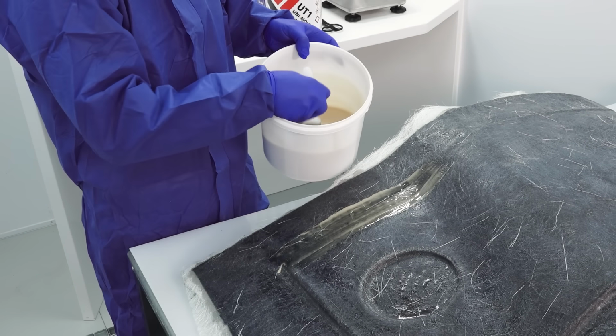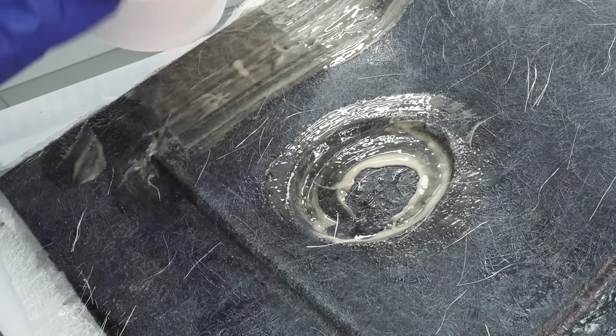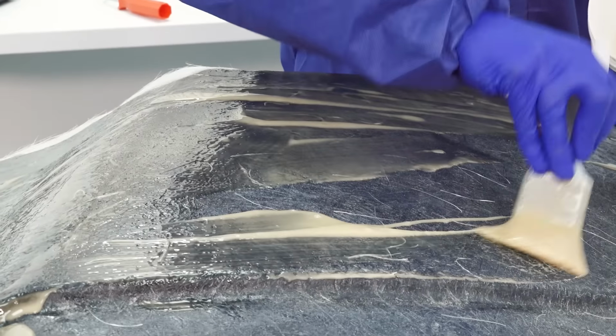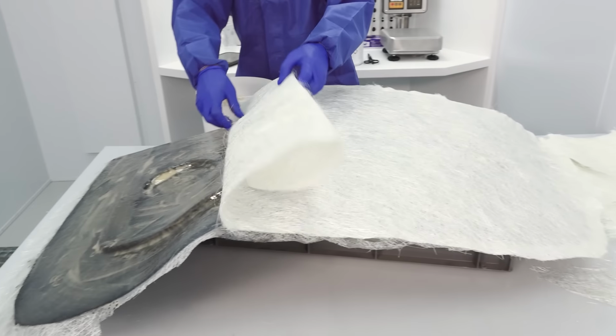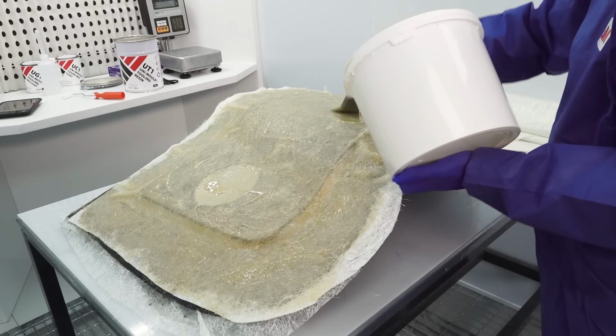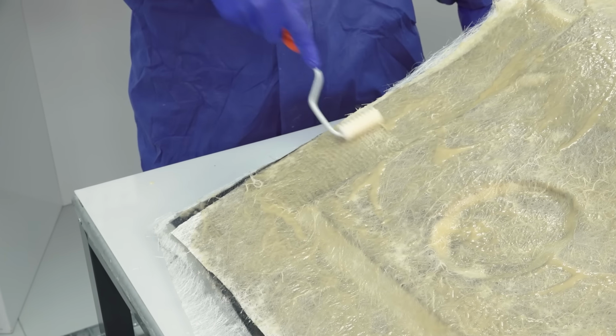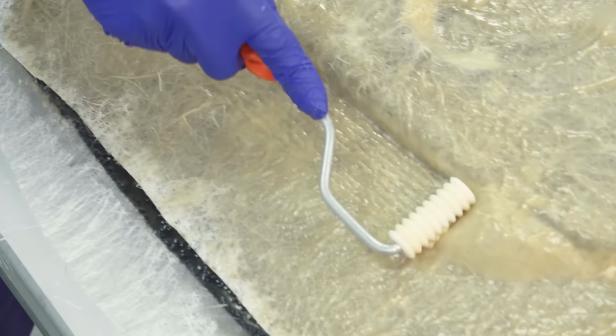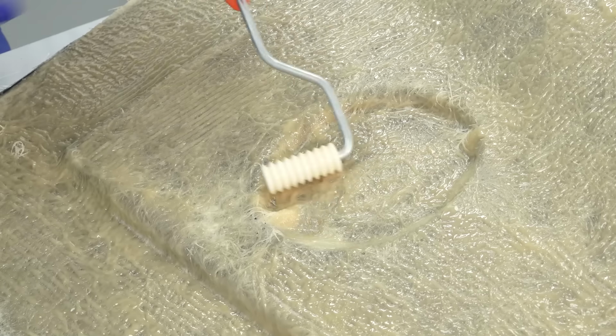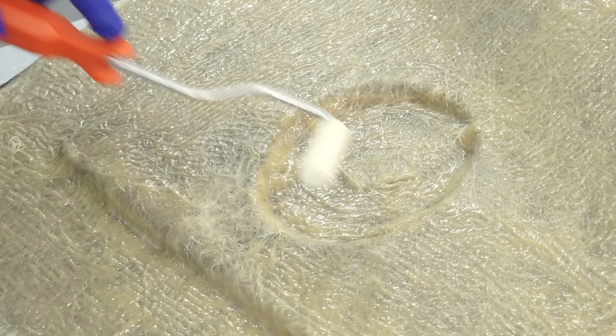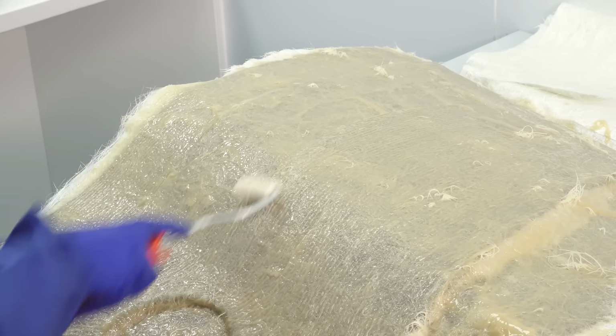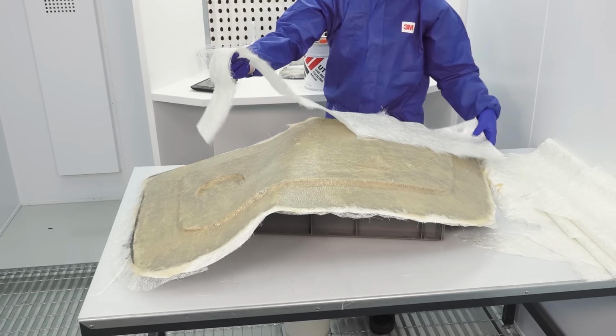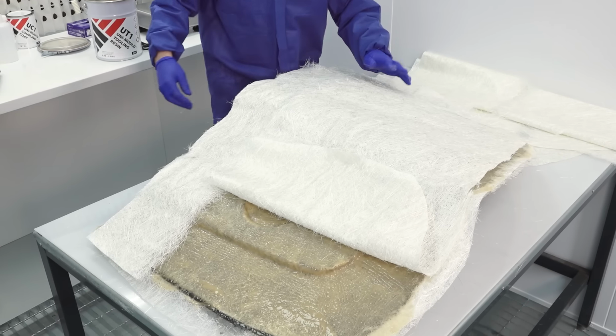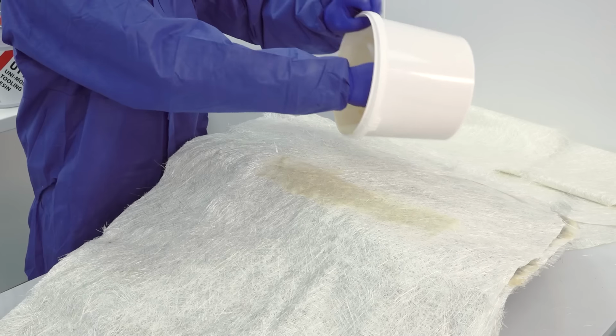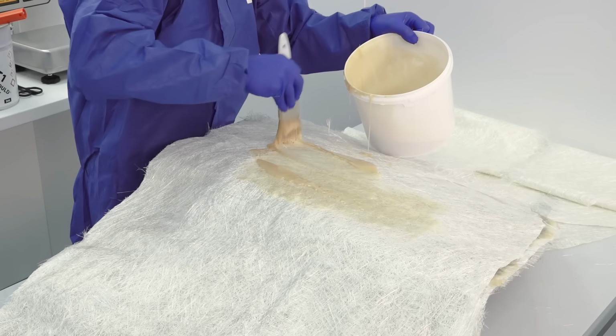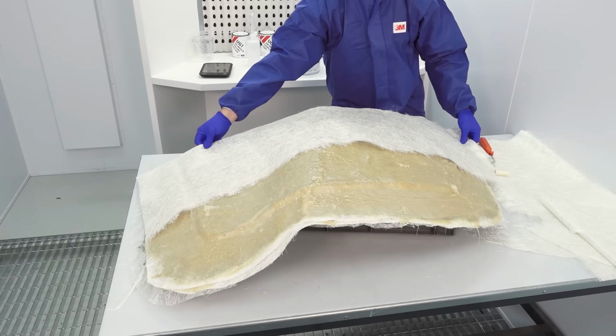Laminating with the tooling resin is much the same as doing traditional fiberglassing. So we apply a thick coat of resin over the entire surface and then drop down a layer of matting and wet it out using a brush and then consolidate with a brush stippling action and a roller until the layer is completely and evenly wetted out and saturated with resin. Then we repeat this for the remaining 3 layers. Unlike normal fiberglass resins, this system does need all 4 layers to be applied in one go to work properly, as it relies on its exotherm to reach a full cure. But because of its special fillers, it's not going to excessively shrink or distort like a normal polyester resin would do.